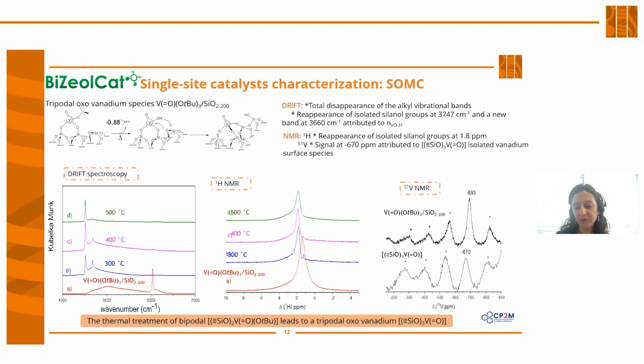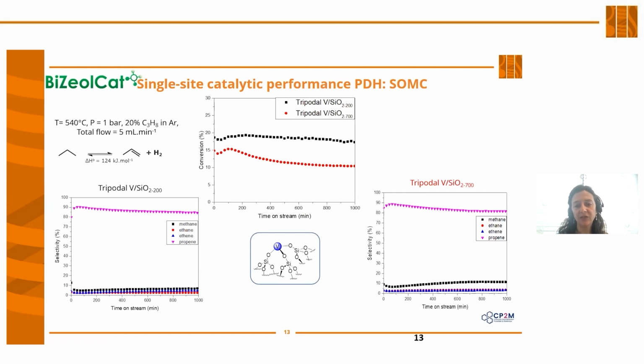Okay, in this case, we used this catalyst, for example, for the reaction of propane dehydrogenation. Here I have the results of the catalyst at two different temperatures of the thermal treatment for the preparation of the single-site catalyst. What you can observe is that when decreasing the thermal treatment temperature from 700 to 200 degrees, we have a higher conversion, and also a higher selectivity. It is remarkable that the conversion can be comparable again to those in the benchmark process, and the selectivity is also quite high.